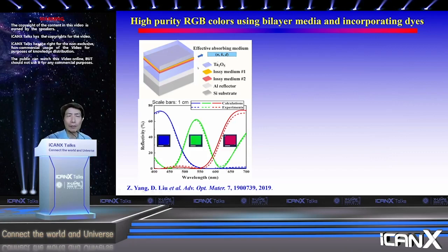So simply put it, right? Here we want to have absorption. Let's say we want to create a green, right? I want absorption in both the red and the blue region. And typical materials cannot give rise to that absorption. So such material, in fact, based on this analysis, doesn't really exist. So what we did is that I suggested they look at a combination of materials, couple materials together to try to mimic what you really want to get, okay? So that's what they did, two layer materials together, and you can actually produce really pure RGB color and very high reflectivity, very bright colors.